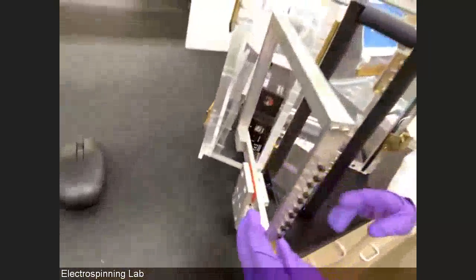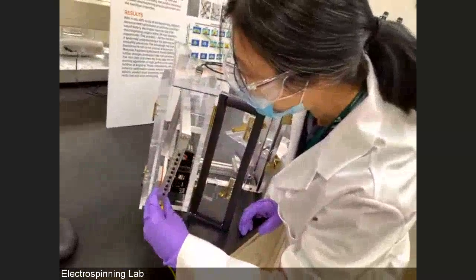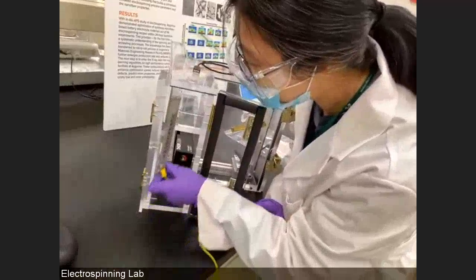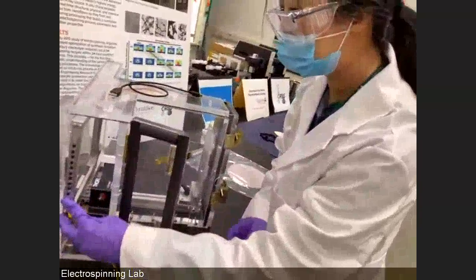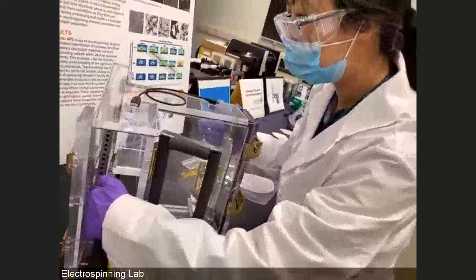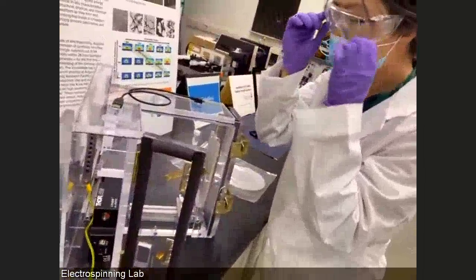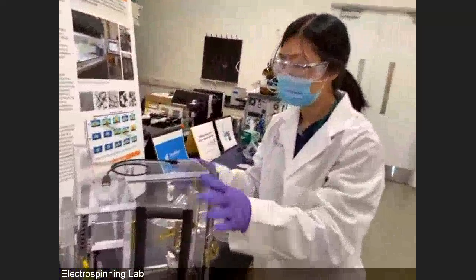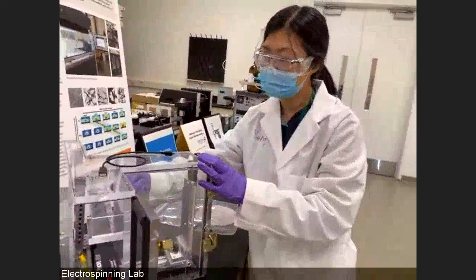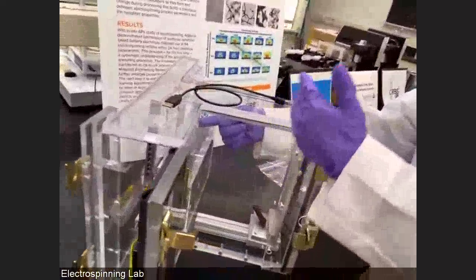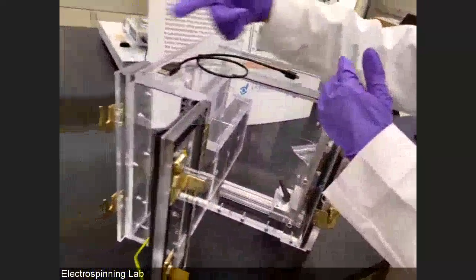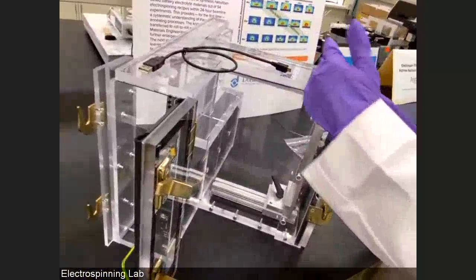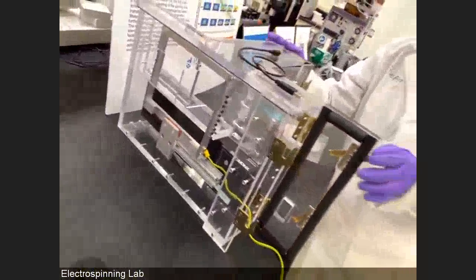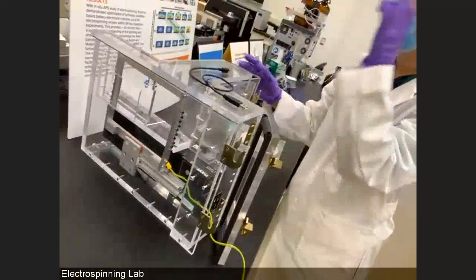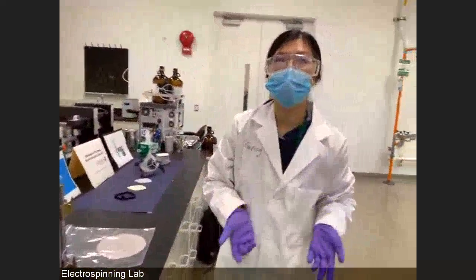And with that, we also have a design that you can see: we have a step motor. After we mount this, with this motor, the collector can move continuously from one end to the other. The reason is the X-ray beam position or geometry compared to the position of the electrospinning setup. We can have an in-situ observation of nanofiber formation, or we can rotate the whole thing this way and the X-ray beam cuts this way. So we have an inline process. With that, we examined 54 recipes over 24 hours.